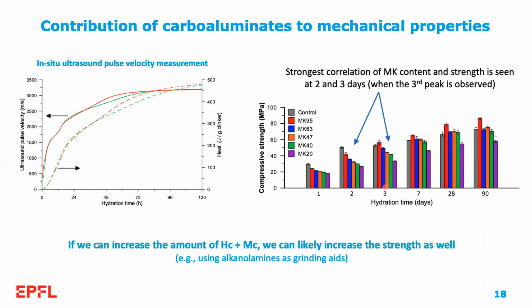For example, by using alkanolamines as grinding aids. This is a side study that we did during my doctoral process. We could confirm that by using things such as TEA, triethanolamine, in the calcined clay, we can not only improve the grindability of the material, but we can also enhance its strength development by promoting the formation of hemi and monocarboaluminate.